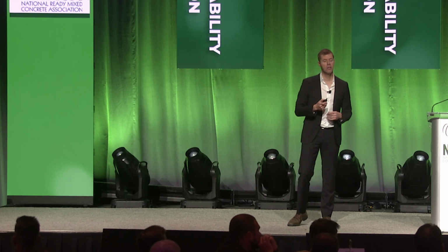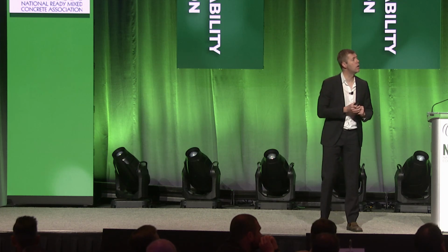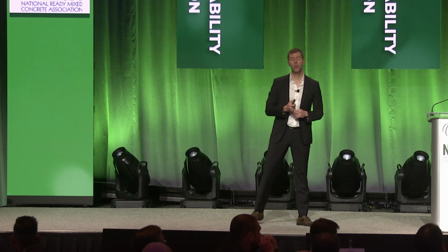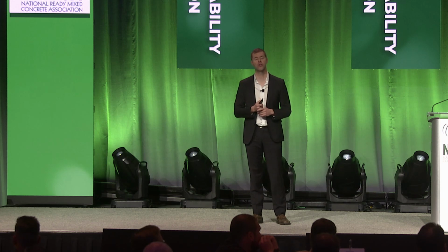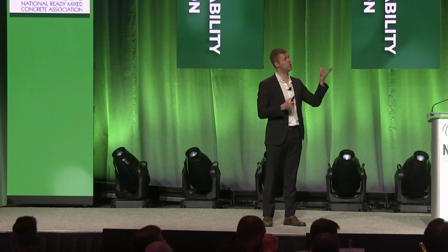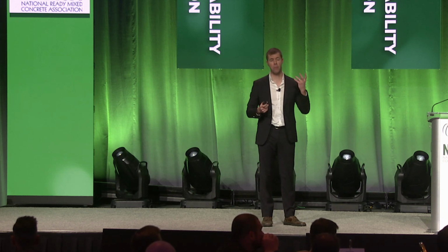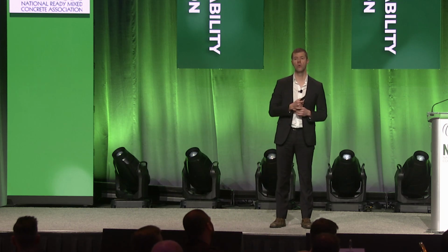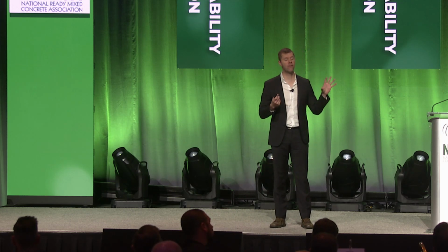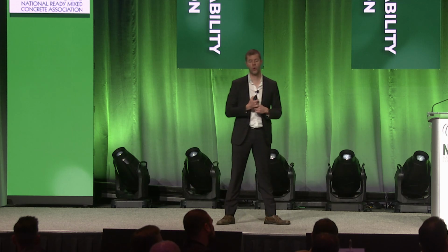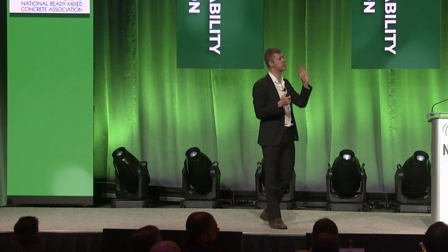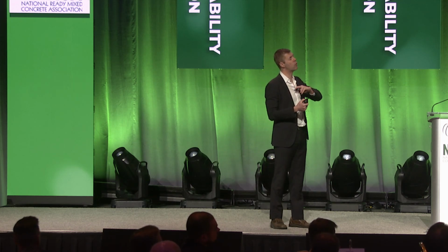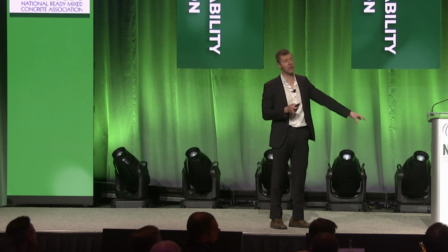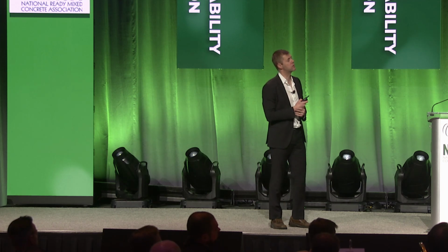It's pretty sweet. So how can we test it? How can we make sure it's right? Well, we made mixtures in the lab where we carefully controlled the moisture contents. And so we should know water cement ratio extremely accurately. And then we'll measure the water cement ratio with the Phoenix, and we'll compare. And for this data set, there's 9 different coarse aggregates, 3 different fine aggregates, different specific gravities, different absorptions, different water cement ratios, different paste contents, and the data looks like this.